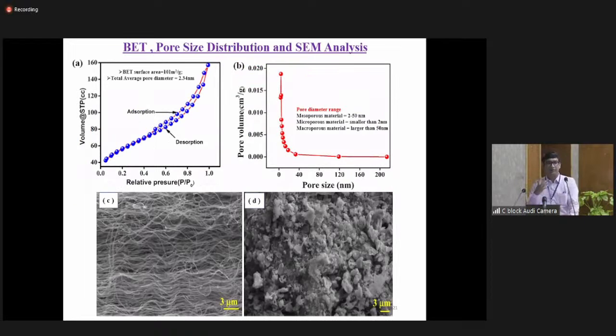After making that material, this is basically carbon nanotube incorporated activated carbon, which is made with the eucalyptus bark. Then we measure their BET and pore size distribution. So BET surface area was reduced. You can see what is happening is the surface area is only 101 meters square per gram. Earlier it was 1800 meters square per gram. And the total pore diameter was 2.34 nanometer.